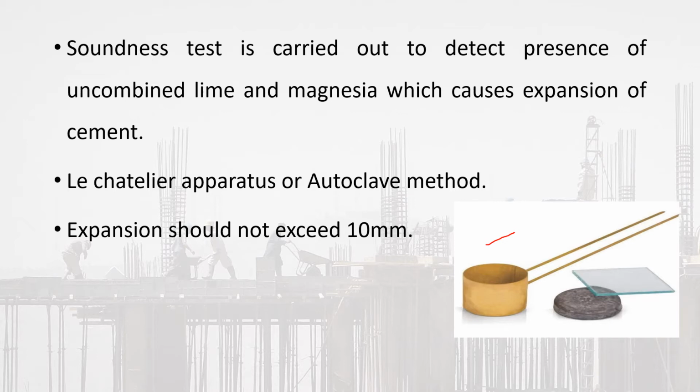The Le-Chatelier apparatus mold is shown in this figure. The cement paste is filled in this mold and it is kept in a thermostatic bath and heated continuously for about 30 minutes, and the expansion of the cement in this mold is noted. According to Indian standard specification, the expansion should not exceed 10 mm for any type of Portland cement. So soundness is an important property of cement, and it is carried out by using Le-Chatelier apparatus or autoclave method.